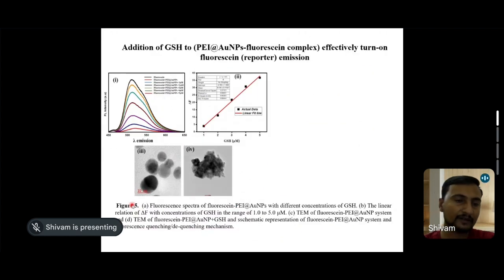But you can see, interestingly, the PEI stabilized nanoparticles quench very well the emission of fluorescein, but after addition of glutathione in the fluorescein metal gold system, a linear increment in the fluorescence takes place. You can see that here. Further, here is the very dispersed nanoparticle, but after addition of glutathione, the nanoparticle gets agglomerated. So, what is the mechanism behind why this kind of phenomenon is happening?